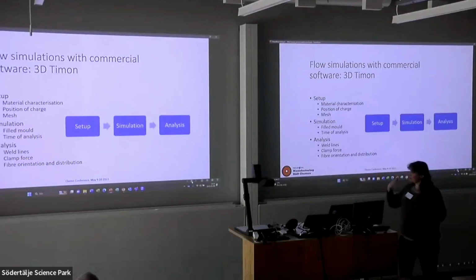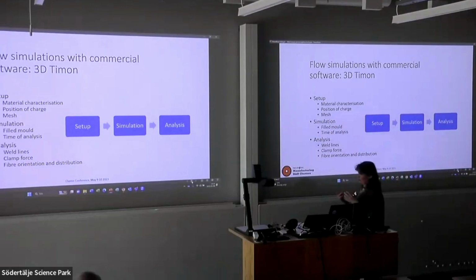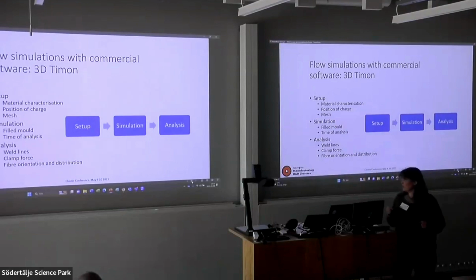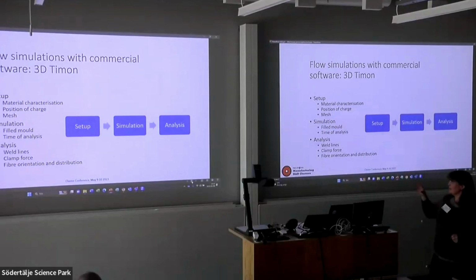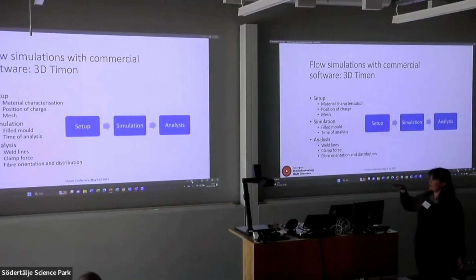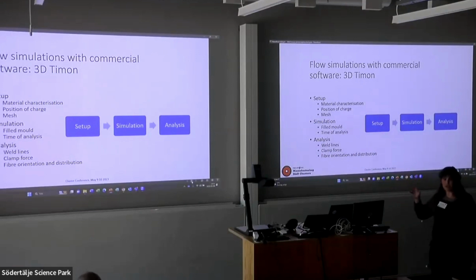So what did we do for the commercial software simulation? We set up the material characterization, we make sure we get the position of the charge right, we look at different meshes to check we've got a mesh that works. And then we do the simulation. We're looking at the filling of the mold and the time of the analysis. And then the analysis is looking particularly at weld lines. These are a big issue when it comes to performance.